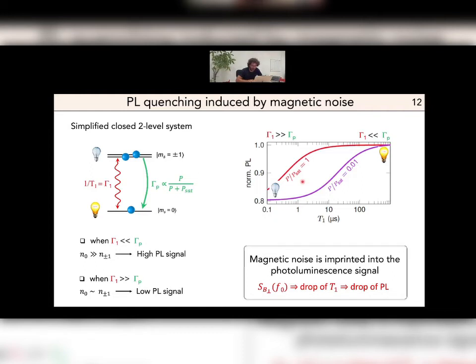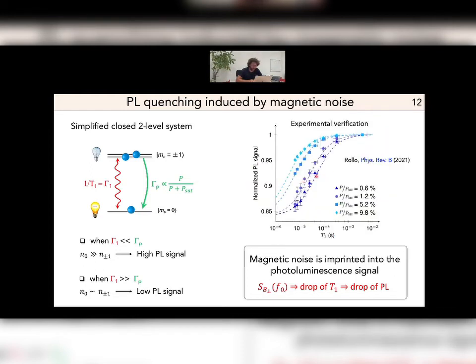So we just verified that experimentally. This is what you can see here, where we have the photoluminescence signal as a function of T1. For that, we use a calibrated magnetic noise source, and indeed you can see that you have a strong drop of the photoluminescence when T1 is decreased.